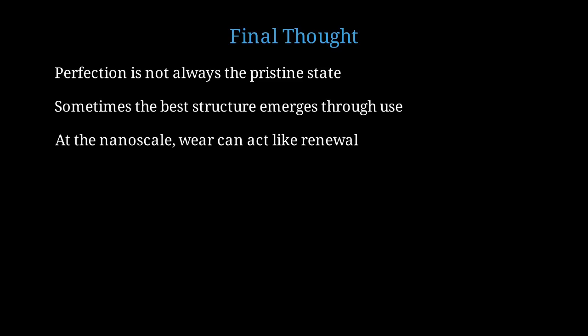Here's a final thought to leave you with. In materials science, we often strive for perfect, defect-free structures, but this research shows that perfection is not always the pristine state. Sometimes the best structure is one that emerges through use, shaped by the very stresses it will encounter in operation. At the nanoscale, wear can act like renewal. Degradation can lead to improvement, and a device can become better the more it is used.